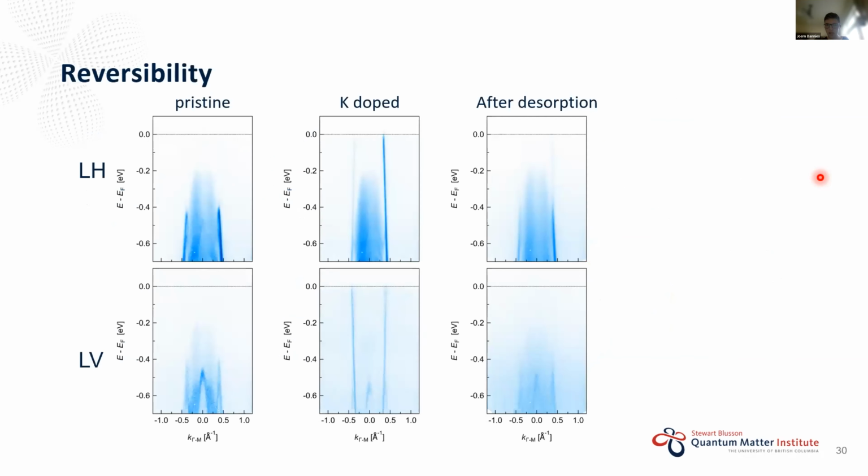So from the experiment, we're limited to whatever we see between the Fermi level and the top of the valence band. So this is 400 millielectron volts. In terms of the theory, between the tight binding model and the DFT, they're in very good agreement. They both give about a 600-700 millielectron volt gap.